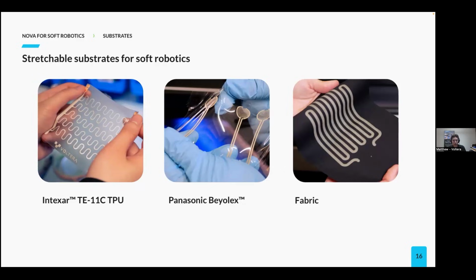For stretchable substrates, some of the stretchable substrates that you can use on Nova for printing stretchable electronics include TPU, Panasonic's Beyolex, and Fabric. So the TPU that we stock is Intexer's TE11C TPU, or thermoplastic polyurethane. And it's a highly stretchable film engineered for stretchable electronics. It's compatible with a variety of stretchable materials as well as Nova, and it ensures robust adhesion for circuits requiring repeated flexing. TPU as a substrate has a high level of recovery, and it's designed for printed circuits requiring repeated flexing and stretching.